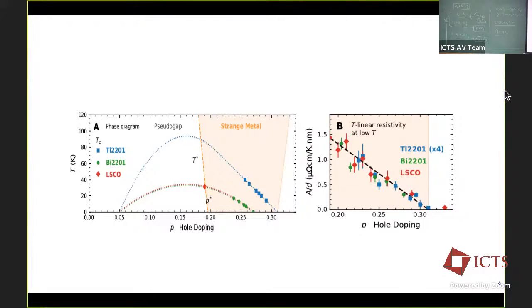Okay, yeah. So this was the observation that I was showing in the beginning and mentioning now, that you have this finite range. And this second non-Fermi-Liquid solution is what we postulate to be an attractive candidate for this phase, where you have significant non-Fermi-Liquid behavior. So now, I showed you the whole machinery and the different solutions, and we went on and solved analytically how this solution looks. For this particular case, when delta is between 1/2 and 1/4, you can analytically calculate the relation between delta and P. In general there is a relation, but even for this 1/4 solution, it's not possible to write a closed form relation between the doping and delta.